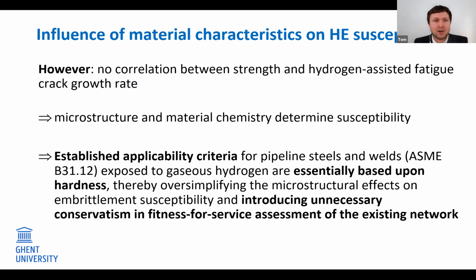It's not the strength and the hardness that is the key factor, it's more the microstructure and the chemistry that dominates the fatigue crack growth behavior in gaseous hydrogen atmosphere. It is therefore not correct that all increases in strength, by definition, lead to inferior hydrogen resistance. Steels of similar strengths are often fabricated also following different heat treatment schedules. And so, because of this, they show a different microstructure, and this will lead not to the same behavior in the hydrogen atmosphere. Therefore, we now have an unnecessary conservatism in the fitness for service assessment of the existing network.